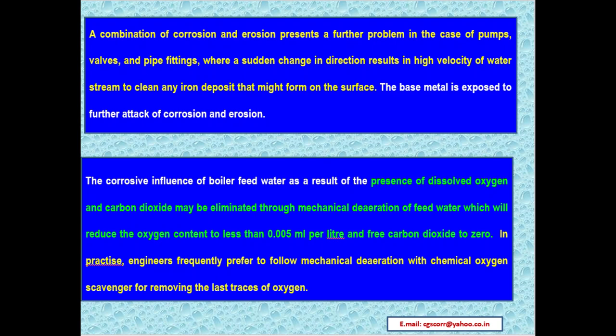The corrosive influence of boiler feed water as a result of the presence of dissolved oxygen and carbon dioxide may be eliminated through mechanical deaeration of feed water, which will reduce the oxygen content to less than 0.005 ml per liter and free carbon dioxide to zero. In practice, engineers frequently prefer to follow mechanical deaeration with a chemical oxygen scavenger for removing the last traces of oxygen.